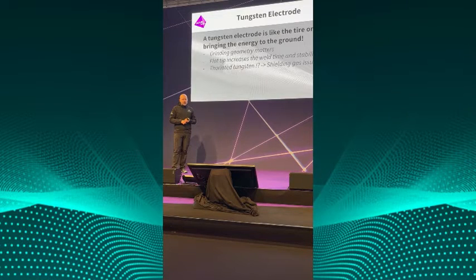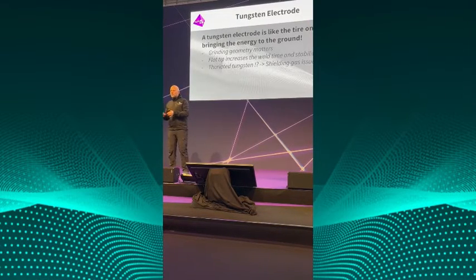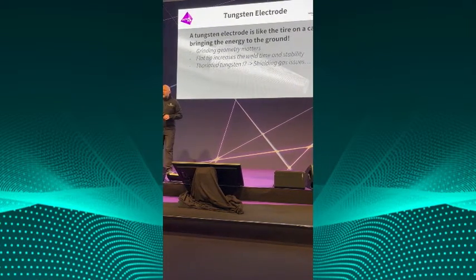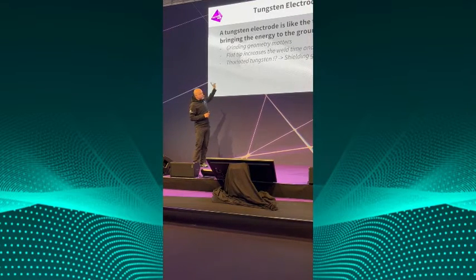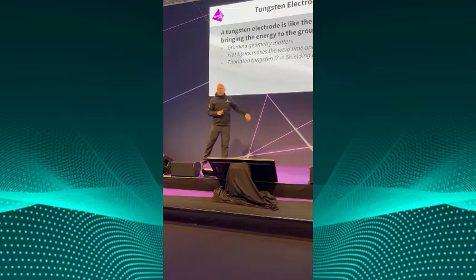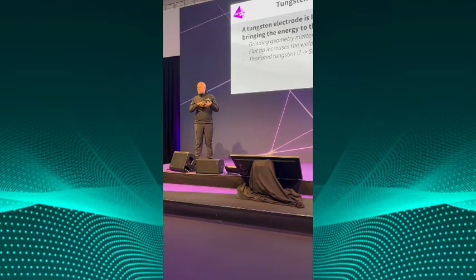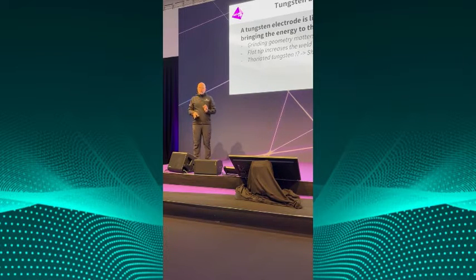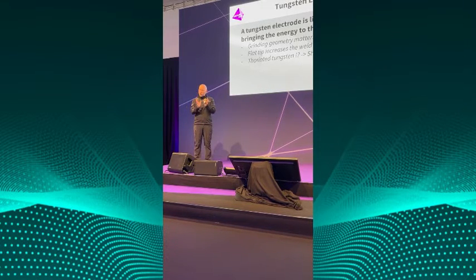Something about thoriated tungsten. We're still happy to produce thoriated tungsten, but in all cases we have so far where a customer stated the thoriated or the red electrode is far superior to anything else, it's tied to a shielding gas issue. I will take every bet that if someone states only thoriated tungsten works, it's related to a shielding gas issue, and almost always he has excessive discoloration, microporosity, things like that, because whatever happens to the tungsten electrode will happen to the weld puddle. This is so closely and intimately related to each other, there's no disconnection of that.